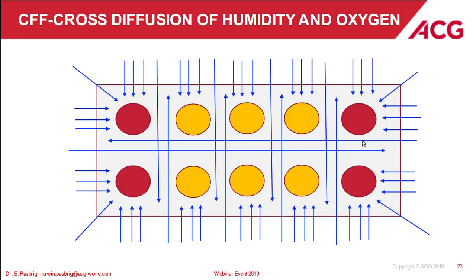Here you see a sketch for related cross-migration. You have on the corner these four cavities in red. These are the cavities that get the main influence over the time from humidity and oxygen migrating through the land area into the cavity. These cavities we are using when we do calculation of cross-migration of oxygen and humidity. We developed together with the IIT in Mumbai a special software so that we can do this kind of calculation.